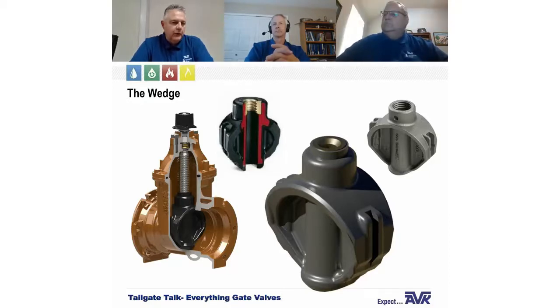But what's the other really good application for NBR in our case? Well, we like using NBR in wastewater because the fats and oils in wastewater are also hydrocarbons, and they can attack and swell the EPDM wedge. EPDM, on the other hand, is excellent for drinking water because it's very resistant to chlorine, chloramines, and ozone. Okay. Alrighty. So it's important for anybody that's listening to understand that if you do have an application where you might have hydrocarbons or something like that outside of the potable water window, AVK does have some options for you.